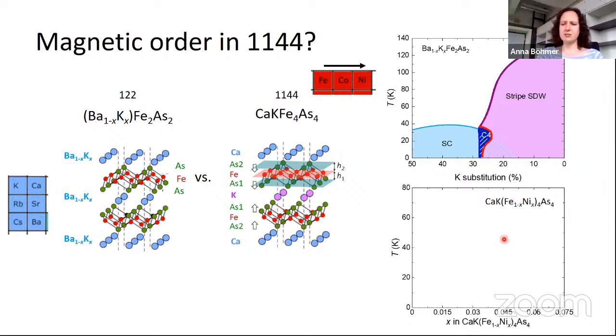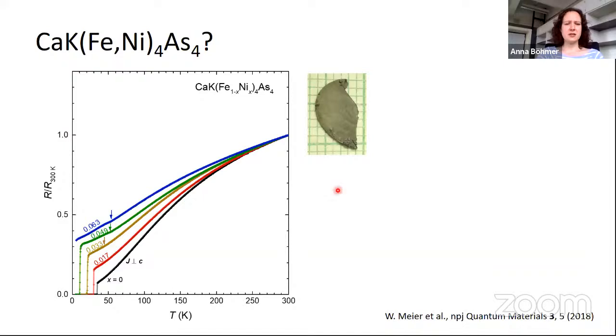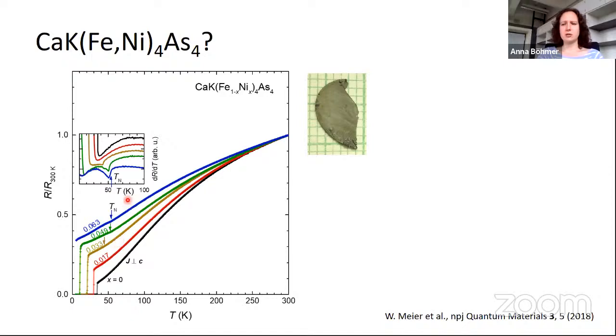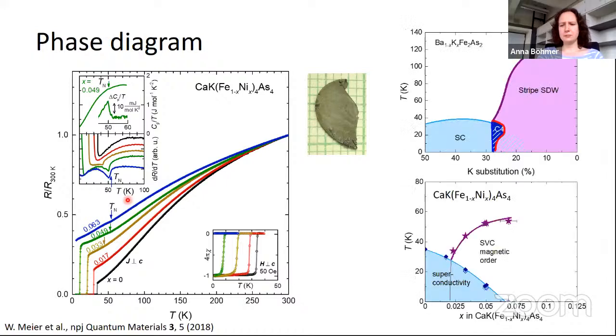So now I have an empty phase diagram here, temperature and nickel content in my calcium, potassium, iron 4, arsenic 4. And we measured resistance, and we indeed found something. So you see the superconductivity, the zero resistance states, and you see little kinks here. You take the temperature derivative of the curves and you see a transition. You put all of this together, and here's my new phase diagram. We have magnetic order here.